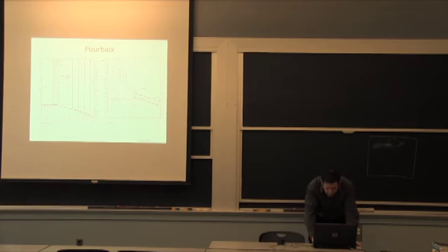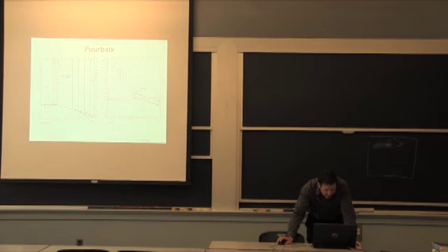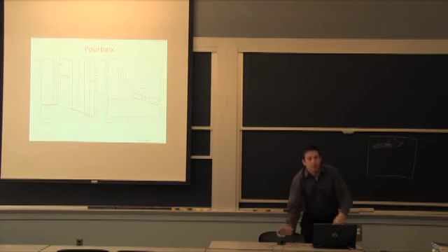Now, in terms of aluminum, we see here the aluminum will go into solution below a pH of about 3. And it will depend how much aluminum. The reason you have 4 lines is it depends how much aluminum you already have in solution. So say we have very little to begin with. So below a pH of 4, we have dissolution of aluminum in our solution.